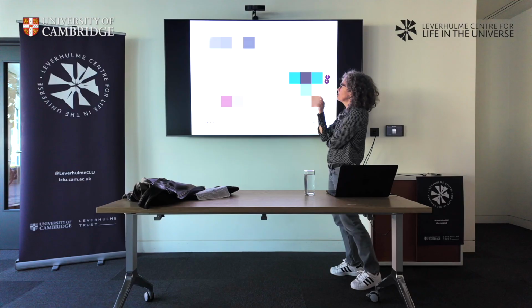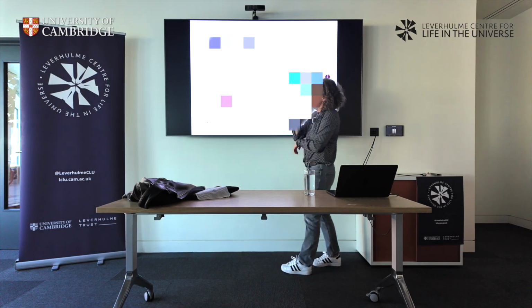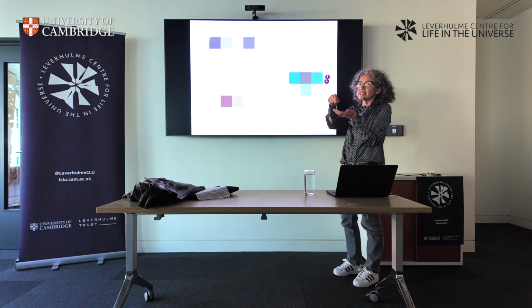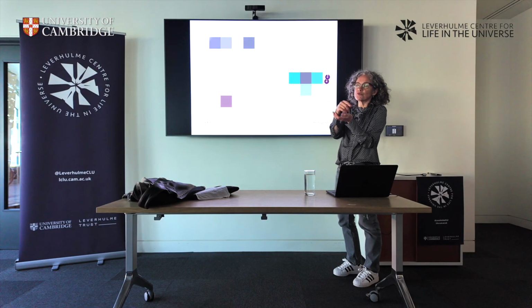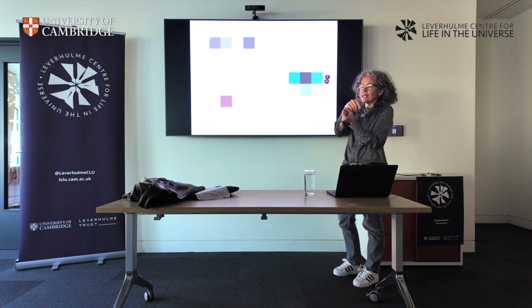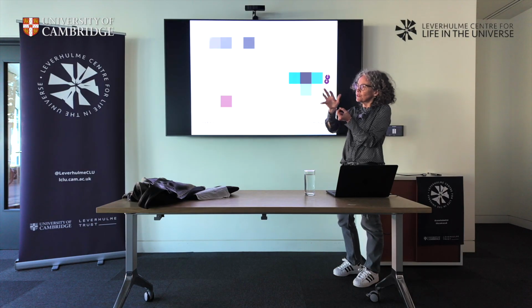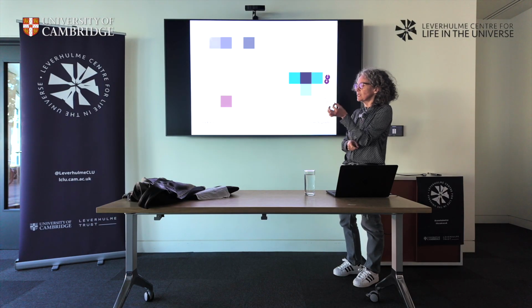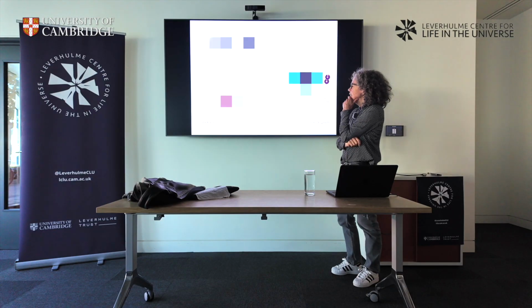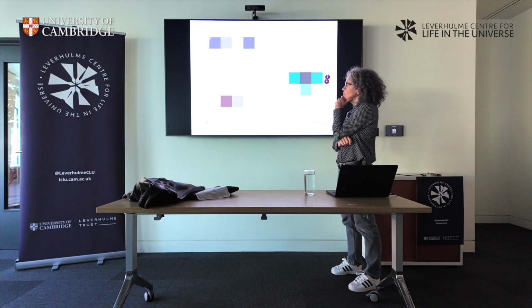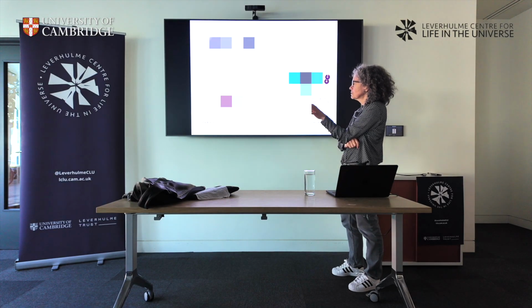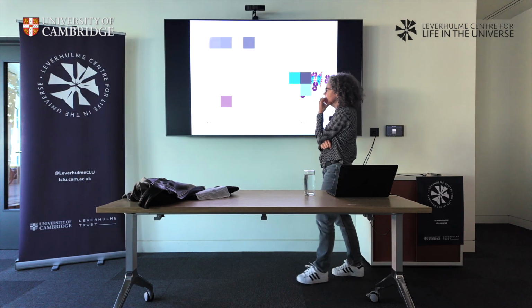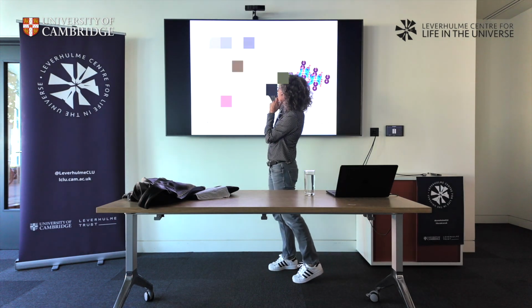So this is X-ray absorption spectroscopy, where you basically scan the next neighbors around your element. It's a chemically sensitive probe. You only get the first shell or first two shells of atoms around the atom you're probing. So we are at the xenon edge. That's a freestanding sample, no pressure, no high temperature, nothing. And you see this signal here.